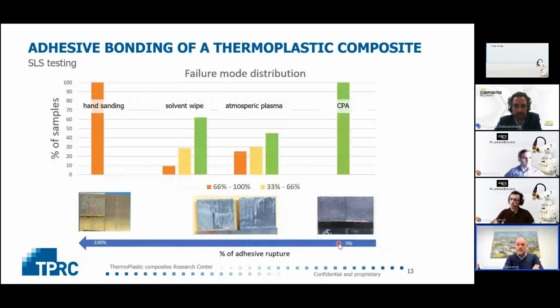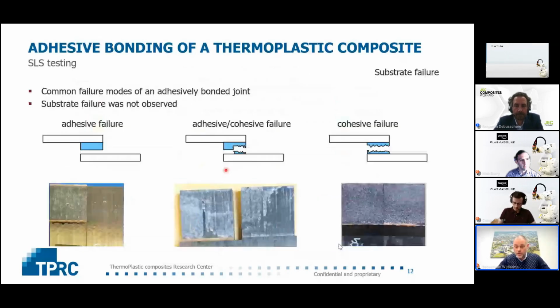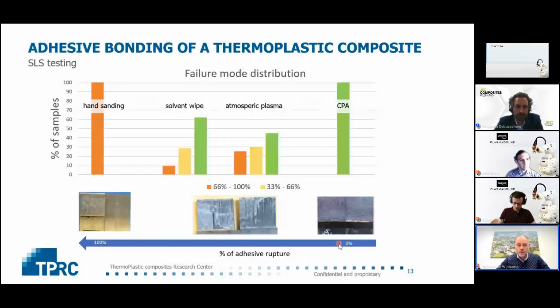And if you look at the amount of samples that failed according to one of these failure modes, we saw that all the hand-sanded specimens failed on the surface, there's a mixed mode with both the solvent wipe and the atmospheric plasma, and with CPA we only observed the cohesive failure. So that's a good sign. That's where we want the material to fail. So it's both low variation and a favorable fracture mode. So that looks really good and promising.